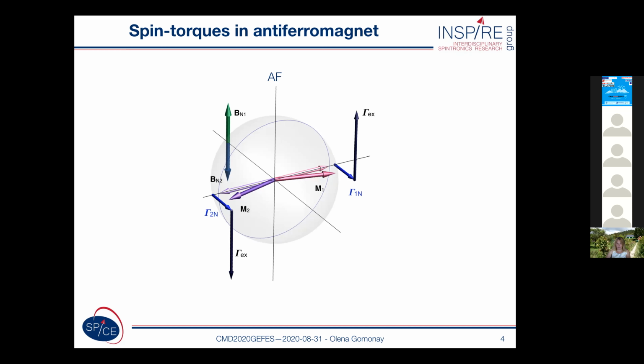opposite magnetic sublattices. And this antiparallel coupling of the magnetic sublattices is kept by an extremely strong exchange field of the order of 1000 Tesla. However, if you cant a little bit these magnetic sublattices, this immediately induces very strong exchange torques, which are labeled as gamma X in the slide. And these exchange torques induce very fast antiferromagnetic dynamics. But another important issue of this type of dynamics is that the canting of the magnetic sublattices is associated with the creation of non-zero magnetization. Although extremely small, as was mentioned in the previous talk, it's extremely important for the dynamics